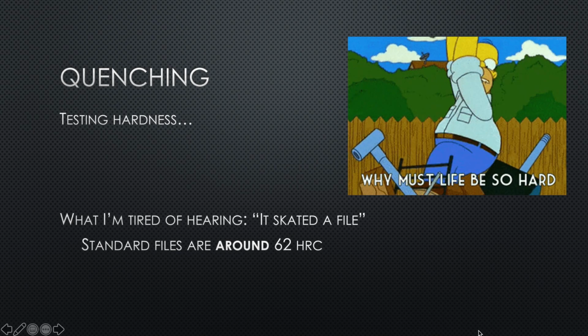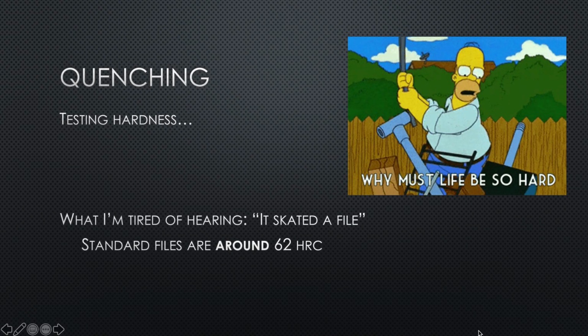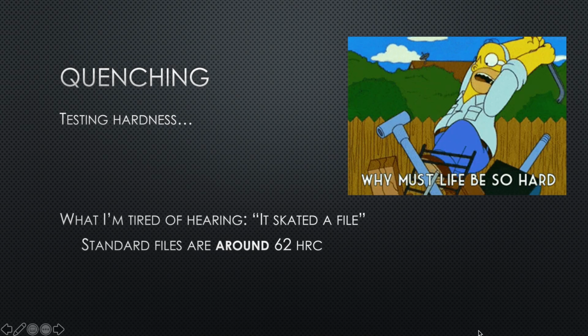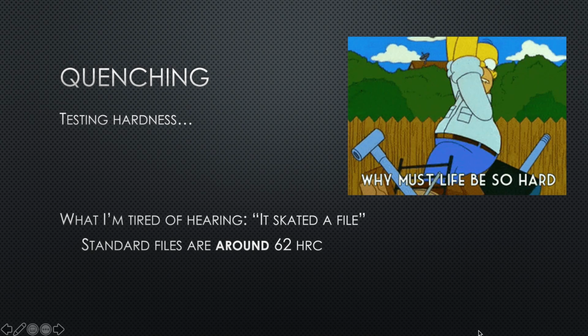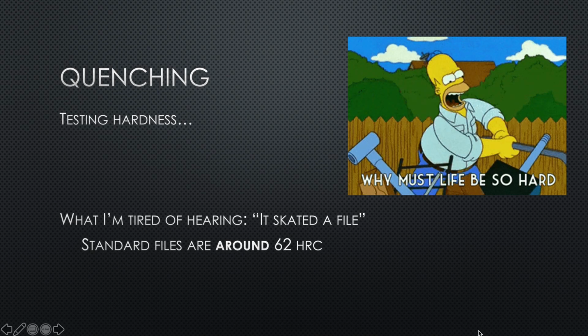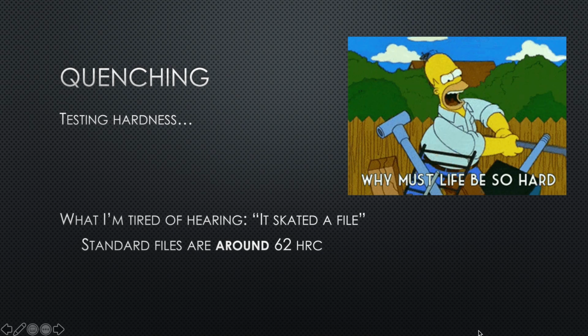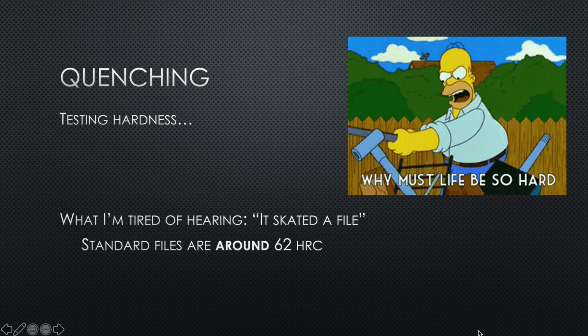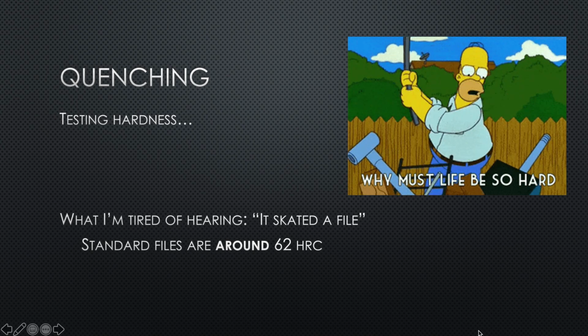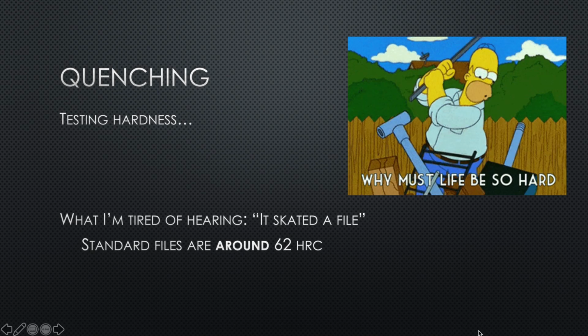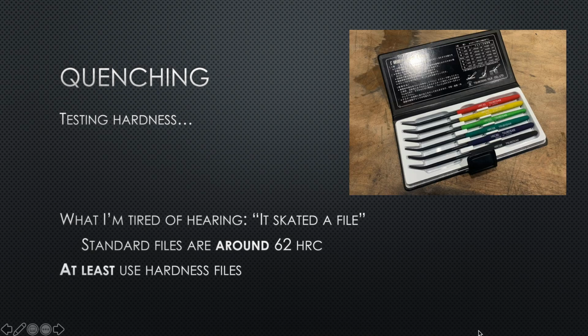Testing hardness. Like I say here, I'm really tired of seeing on Facebook, it skated a file, it worked for me. Those files, just a normal Nicholson, if it's even a Nicholson file, may be around 62 HRC. A lot of your steels, when they come out of the quench, are going to be around 65. So the fact that it skated a file doesn't really tell you anything. That might tell you that it's at about 60 coming out of the quench, which is not very good. At least use hardness files. I've got a picture here of what the hardness files are. These are just files specifically for hardness, and they're in 5-point increments. So you can test with a 65, test with a 60, and the nice thing is you can feel the difference. And these are guaranteed to be those levels.